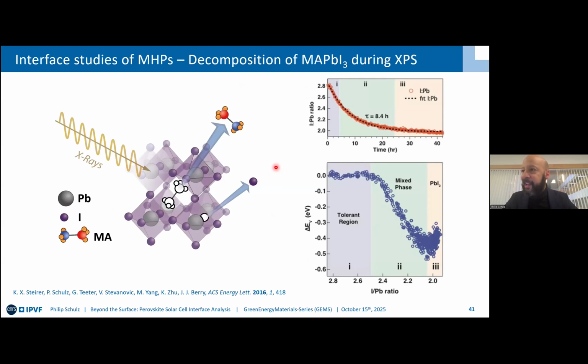Were there any issues in taking these type of data? So yes, I said it initially, you need to be very careful about this. We had this long-running experiment here for an XPS measurement for 42 hours. This was almost 10 years ago now, of just MHPs. And then we could see clearly that the iodine to lead ratio was dropping off over time. We're losing methylammonium, we're losing iodine.